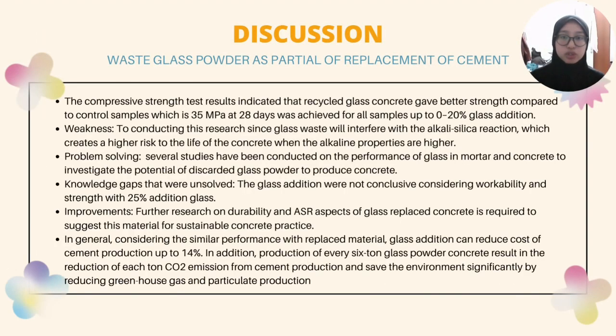Okay, next we jump into the discussion of the waste glass powder. Firstly, the objective can be proven when the compressive strength test result indicated the recycled glass concrete gave better strength compared to the control sample. 35 megapascal at 28 days was achieved for all samples up to 20% of the glass addition.